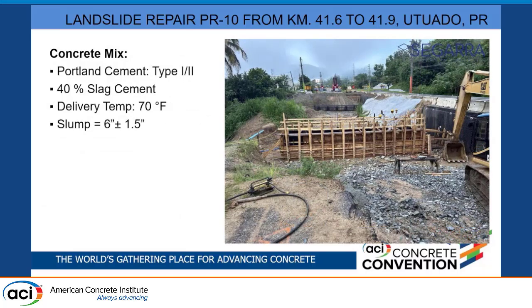What we planned with the concrete producer and with the contractor was to use type 1-2 cement from Argos, 40% slag as a substitution. The delivered temperature was 70 degrees, using a lot of ice per cubic yard, and a slump in the range of 6 inches plus or minus 1.5.